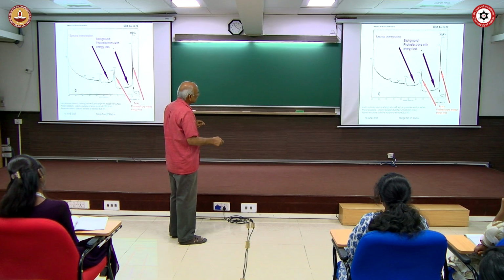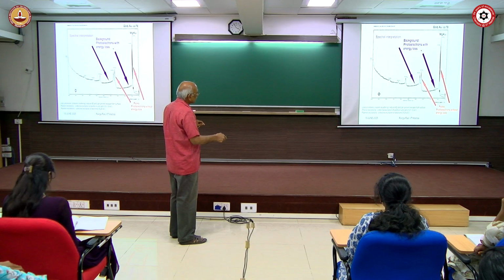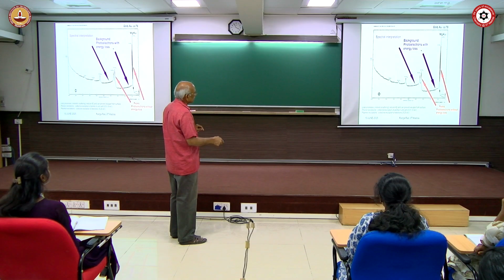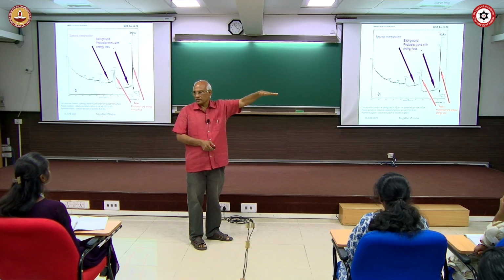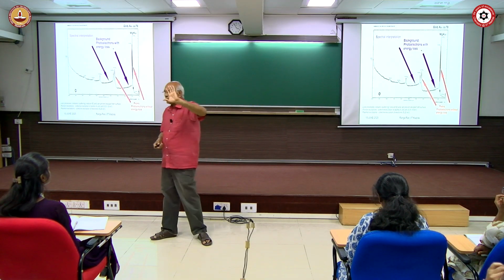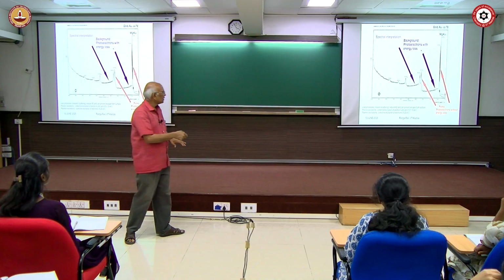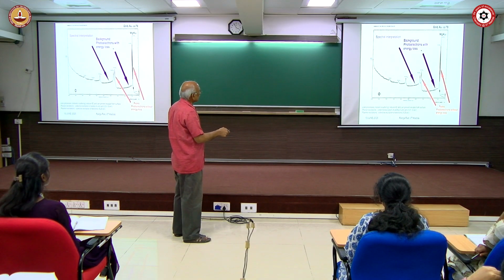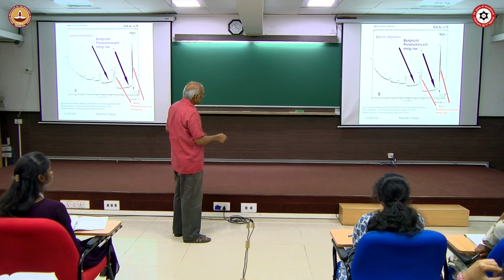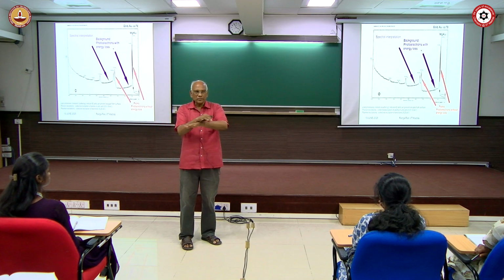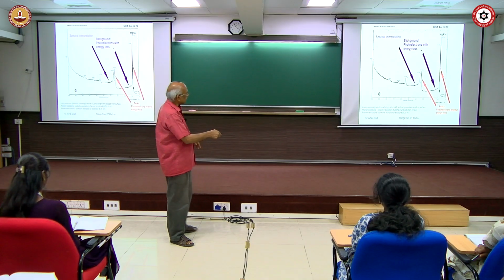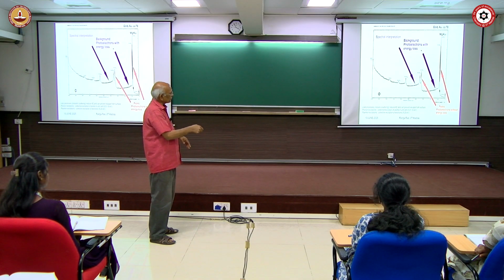This spectrum has, see the red lines, these are basically the peaks of photoelectrons without energy loss. These are the electrons which are coming from the top layers without losing any kinetic energy. They are the ones which are giving the correct spectrum. Now, you see the background, photoelectrons with energy loss. These are all electrons which have lost their energy. They form the background. The actual spectrum is superimposed on the background.